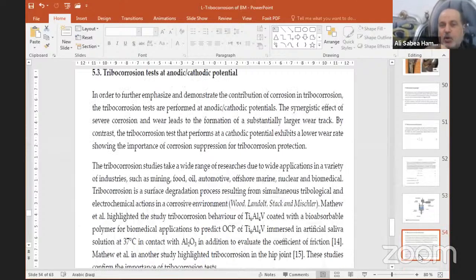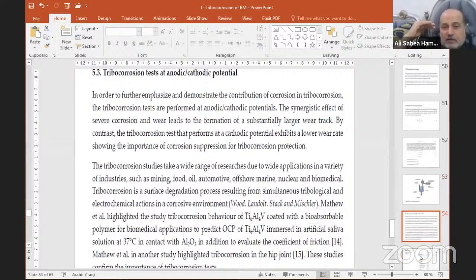Tribocorrosion test at anodic and cathodic potentials. In order to further emphasize and demonstrate the contribution of corrosion in tribocorrosion, the tribocorrosion tests are performed at anodic potentials and cathodic potentials. Corrosion and wear lead to formation of a larger wear track. The tribocorrosion tests performed at cathodic potential showed lower wear rate.